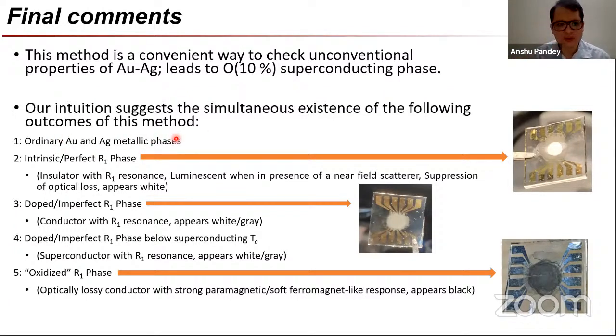So ideally, one would not like to have the AuAg metallic phases, but these can exist if there is a stoichiometric error in the addition of gold silver, or because of structural degradation of the sort which I have shown earlier. If you hold these films for a very long time, it seems as if they do figure out occasionally ways to degrade where silver and gold segregate. There is something which I would call an intrinsic or perfect R1 phase, which we now hypothesize is a pure insulator. This is essentially a solid which you get, which is unusually white, and it's even luminescent in the presence of a near field scatter and has completely suppressed optical losses.